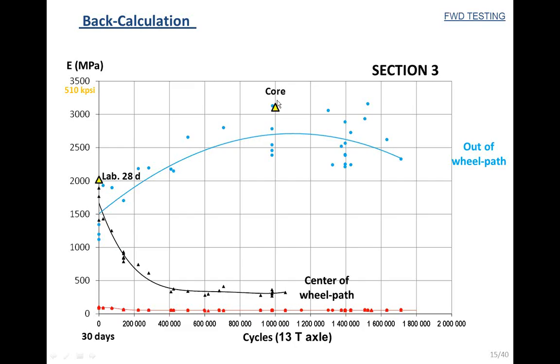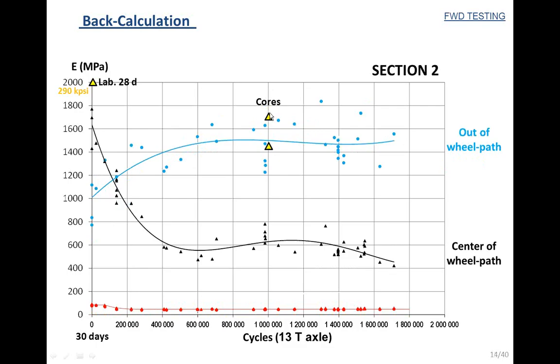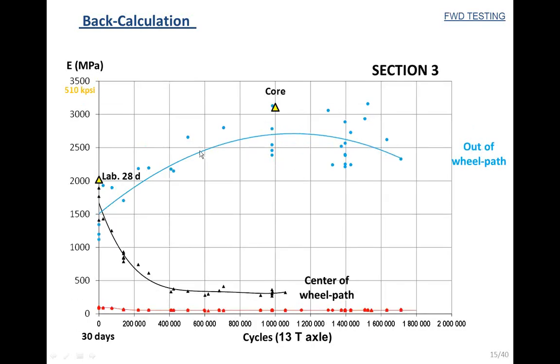I should say that we also extracted one core at cycle 1 million, in the non-loaded line out of the wheel path, and we saw that the modulus that we obtained in the laboratory for the core was very similar to the modulus that we were obtaining from back calculation. Now I'm going back to section 2, and in section 2 we have the same result. The modulus that we obtained for the cores were very similar to the modulus from back calculation. So these moduli represent the material with no damage, and these represent the material with damage.